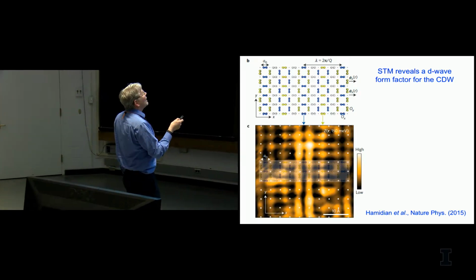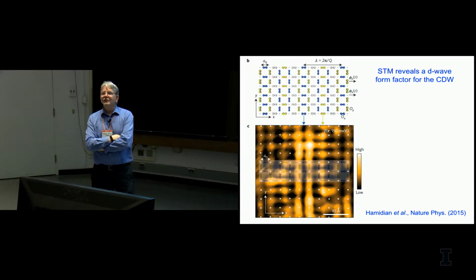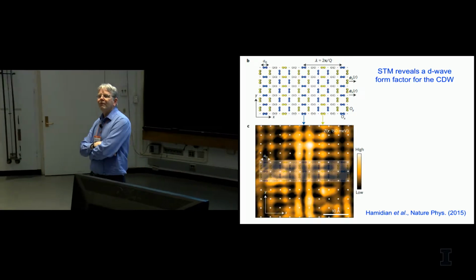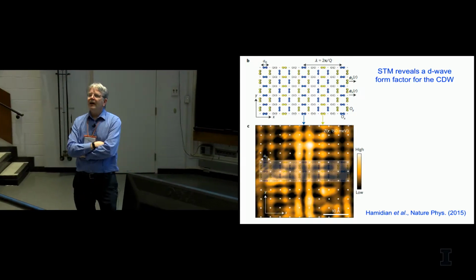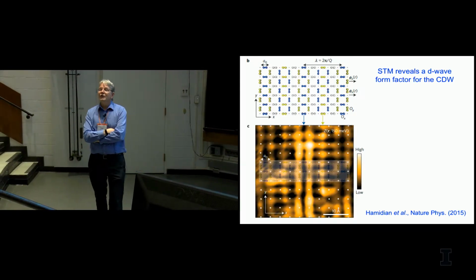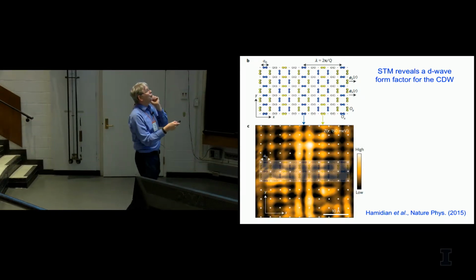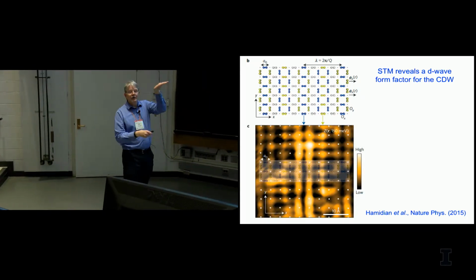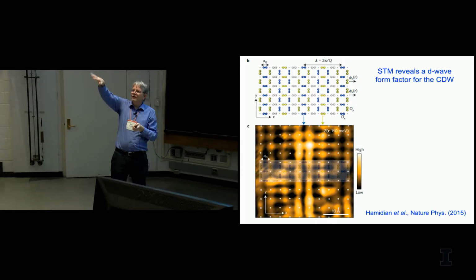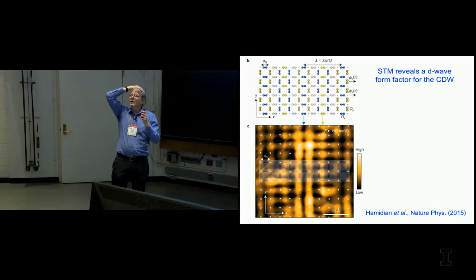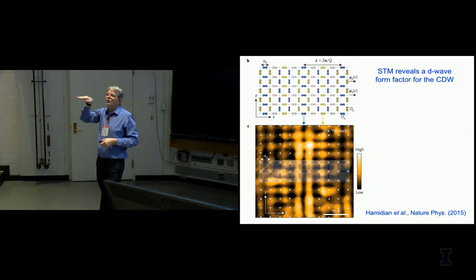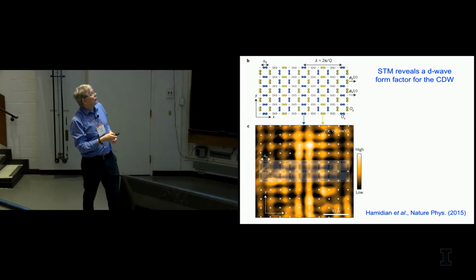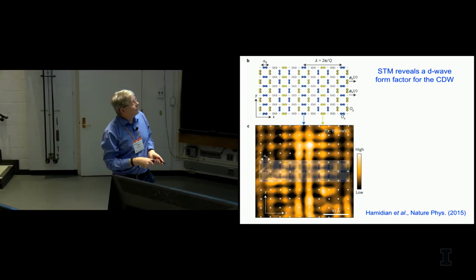The interesting thing seen by STM, though, is that this is actually a D wave, has a D-wave form factor. In some sense, this state is a particle-hole conjugate of the D-wave superconductor, in that if you look at the phase factor, so you have charge density wave going this way and in the orthogonal direction, they're out of phase by pi over 2 as you go from the x to the y direction, so they have a D-wave-like form factor.